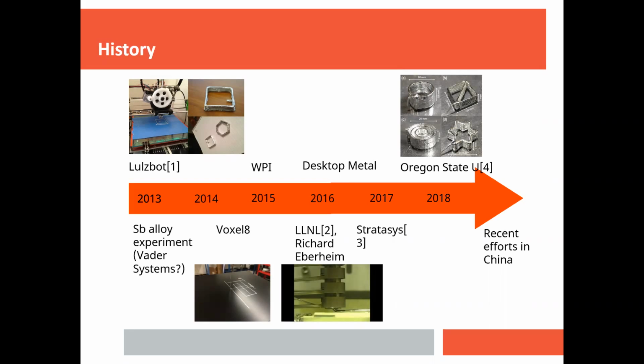And then Desktop Metal and Stratasys as well attempted to 3D print this way. I believe also 3D Systems at some point, but I wasn't able to find where that was in the timeline. More recently, Oregon State University had what I consider the first successful semi-solid metal prints. They used really a metal matrix composite. It wasn't a semi-solid alloy, but they introduced nickel nanoparticles into gallium metal. And with that, they were able to 3D print various structures. And with it, basically, you produce a fluid with a yield stress. And then there's been more recent efforts in China, but those have also started to peter out.